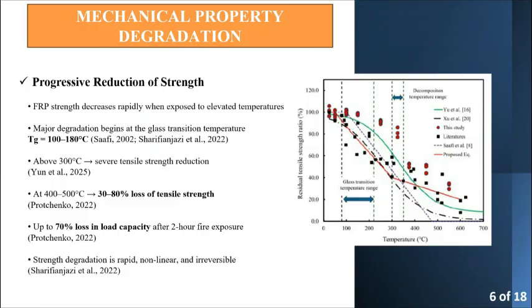Some studies also found that if the temperature rises above 300 degrees Celsius, the strength drops significantly. At temperatures between 400 and 500 degrees Celsius, FRP can lose between 30% and 80% of its original strength, as Protchenko have already mentioned in their studies. It is also important to understand that this strength loss is not gradual. It happens quickly after exceeding Tg, and the damage is permanent even after the structure cools down. So FRP reinforcement loses strength rapidly under fire, which can seriously affect the safety of the structure.